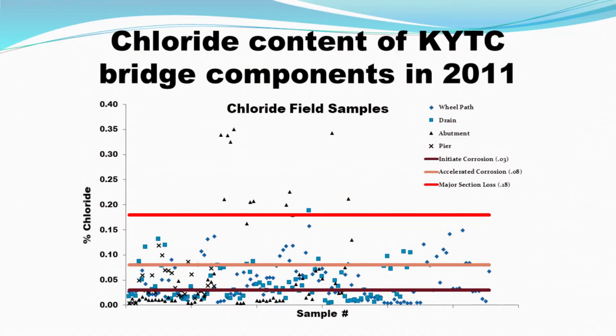Testing was done again at about 2-inch depth, looking to see what the chloride content was presumably at mat depth. It's a very busy slide, but what you can take away from this slide is, with all the sampling done, more than 50% of all the samples taken were above the action level. So for chloride ion penetration, the decks tended to be the lowest because they're designed to drain.